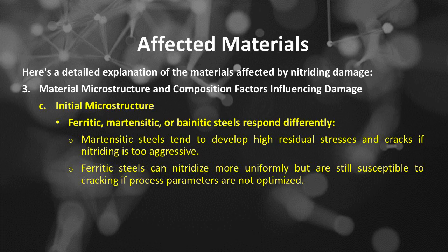Number C, initial microstructure. Ferritic, martensitic, or bainitic steels respond differently. Martensitic steels tend to develop high residual stresses and cracks if nitriding is too aggressive. Ferritic steels can nitride more uniformly but are still susceptible to cracking if process parameters are not optimized.